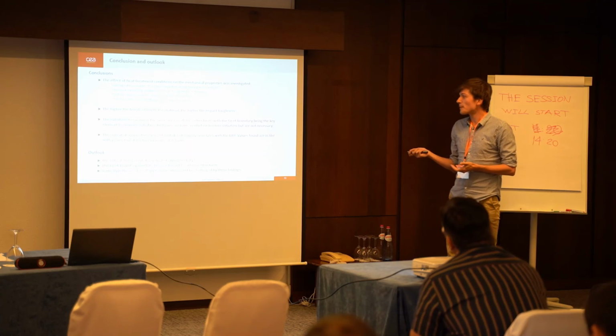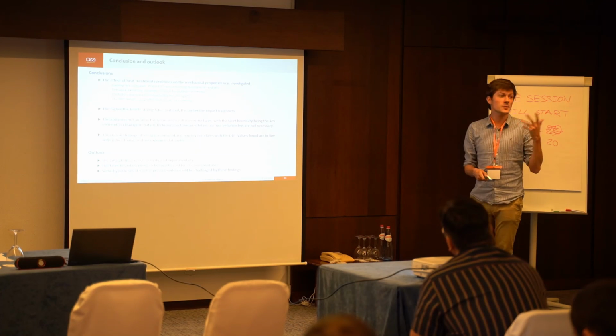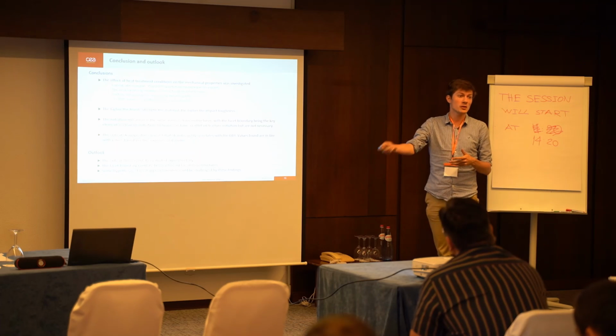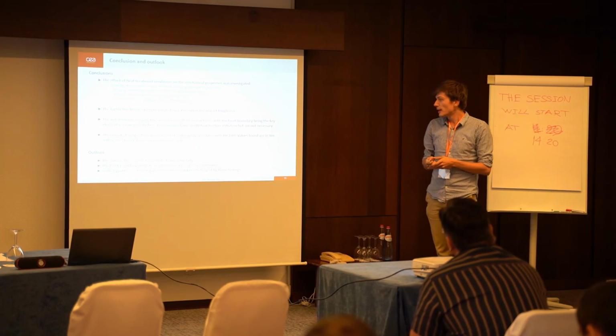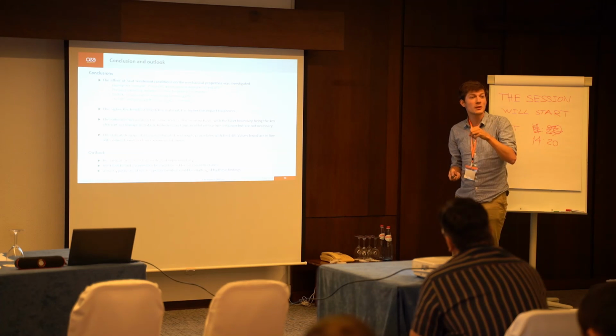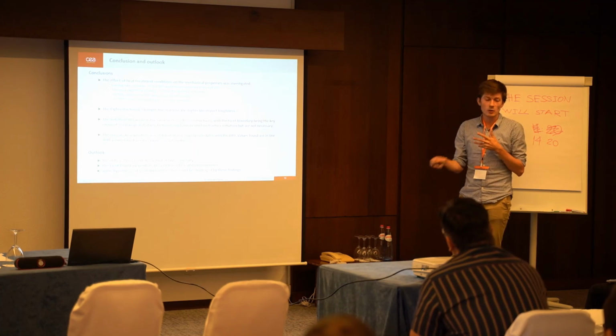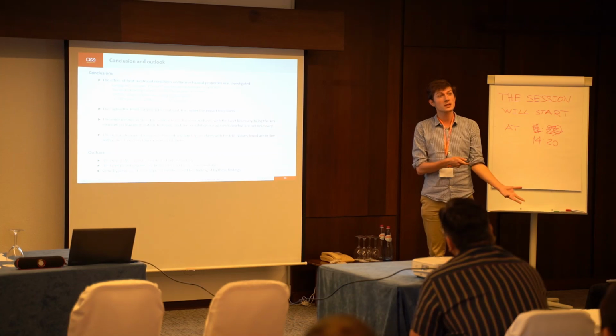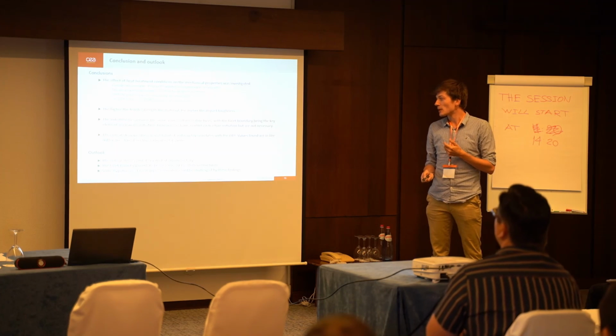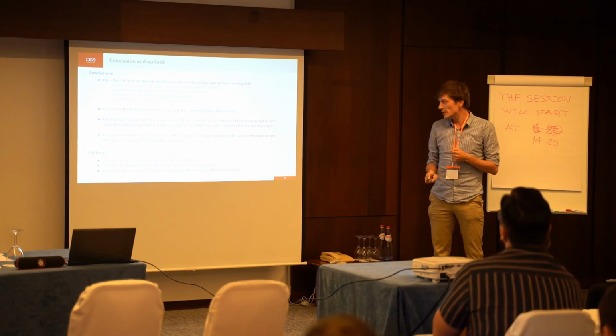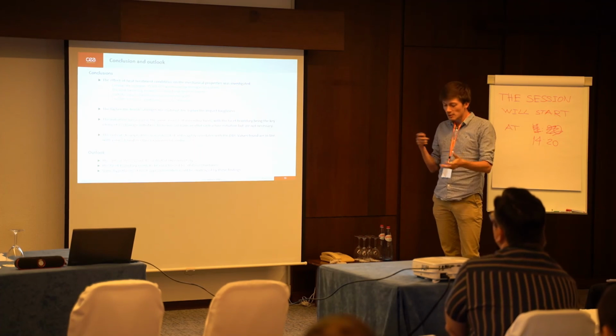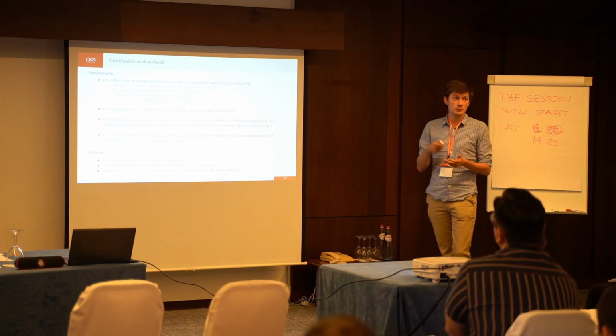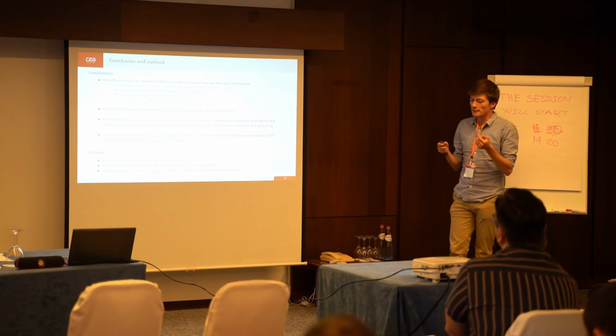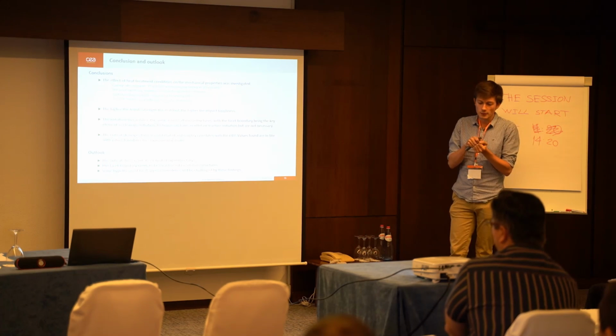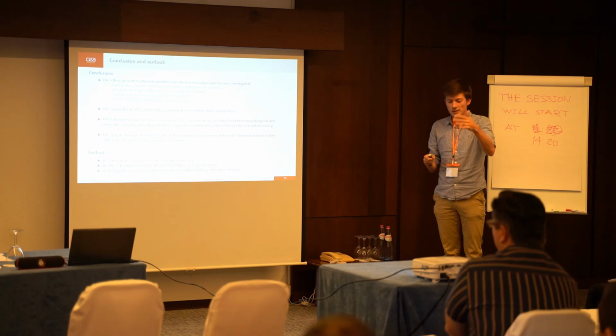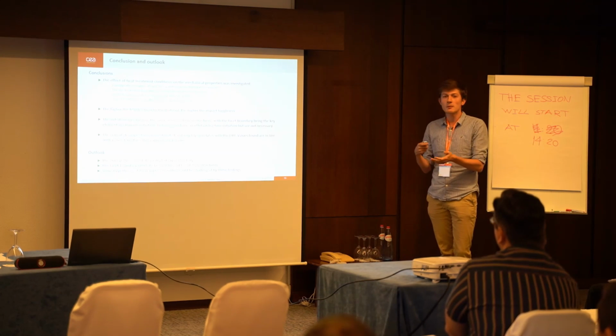For future work, the critical stress will need to be evaluated experimentally to validate the estimation that we had from the impact test. The facet boundaries that we observed will also need to be completely characterized across all microstructures to see if there are any differences that would explain the difference in impact toughness properties. And finally, these results suggest that some hypotheses of local approach modeling of brittle fracture, which usually assumes initiation on brittle particles that fracture at the onset of plastic deformation, could maybe be improved.